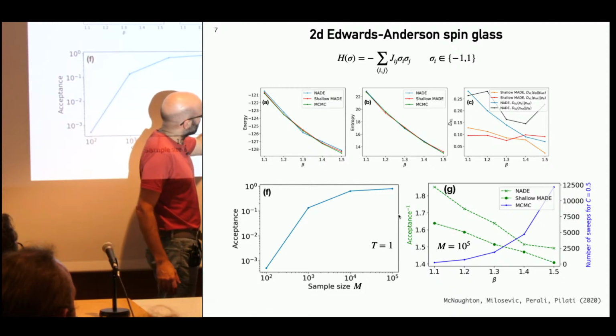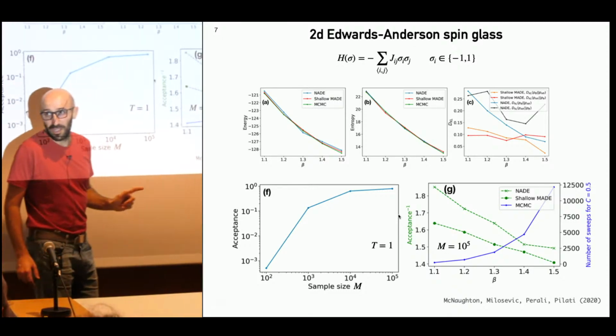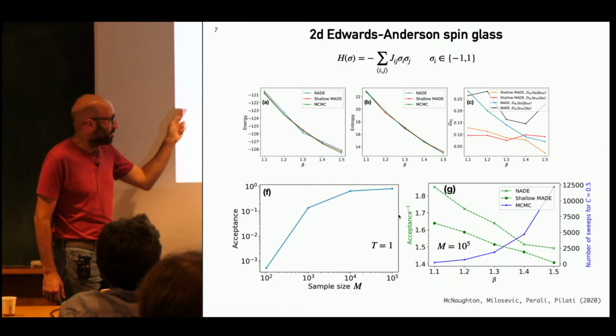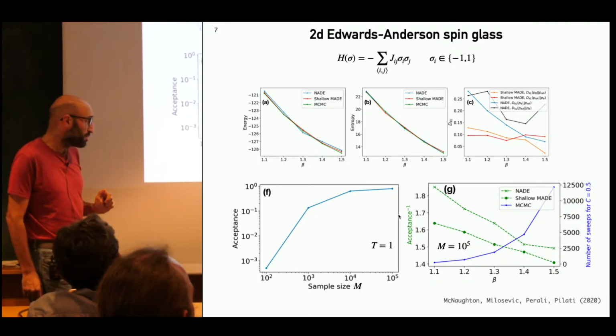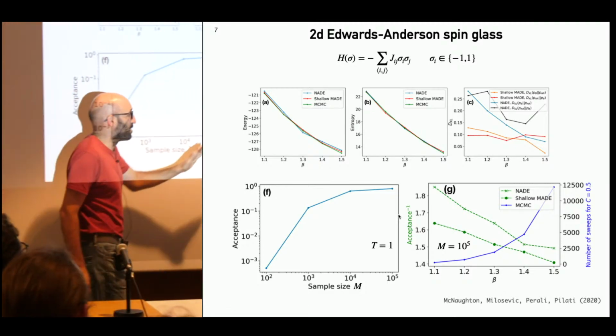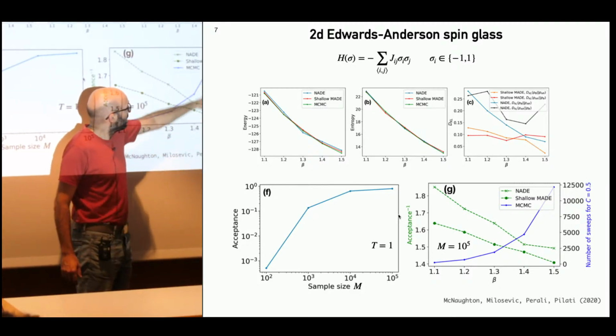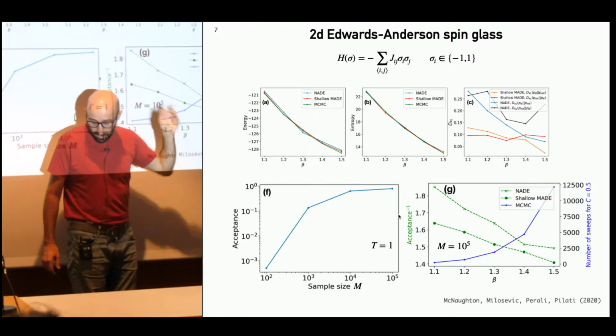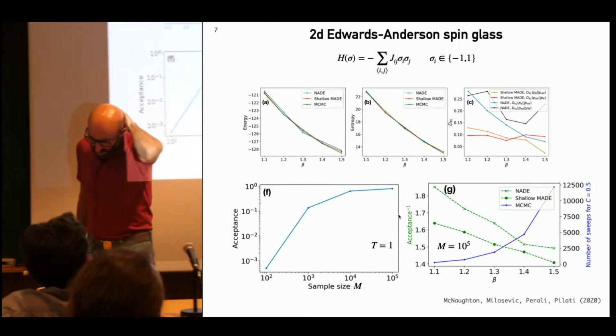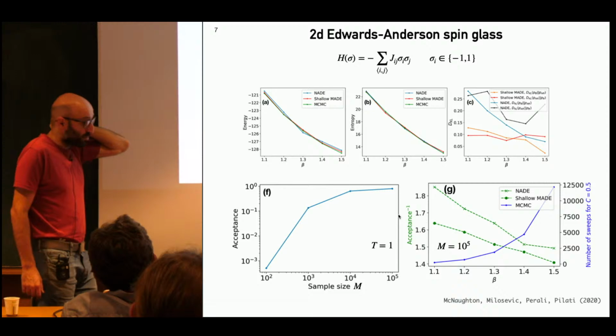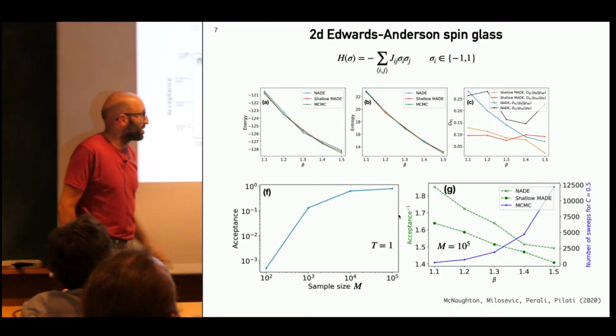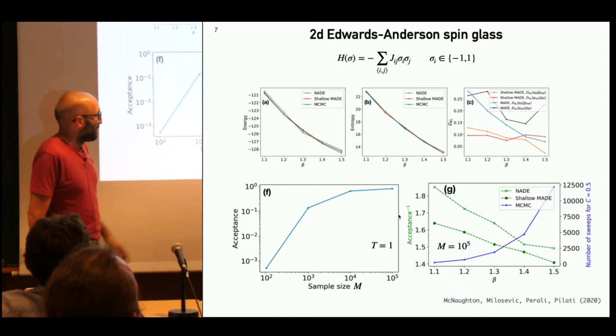And it actually goes down with temperature. So it becomes even faster when you decrease the temperature. So this is very good, because when you are at this temperature here, you get a huge speed up. In terms of computer time, it's about 5 orders of magnitude speed up with respect to the local MCMC. So we are happy.